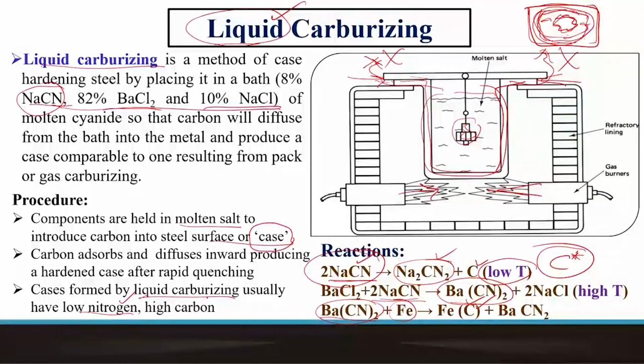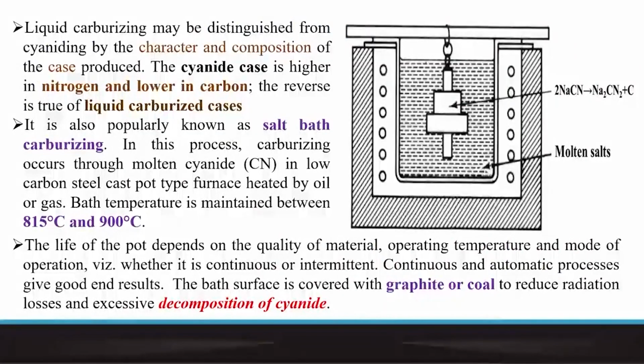So this is to be distinguished from the other carburizing processes in terms of the character and composition of the case that we produce. The cyanide case is higher in nitrogen and lower in carbon, and the reverse is true when we are doing with the liquid bath process. Okay, so it's essentially a salt bath, and the temperature that we are talking about is slightly lower than the pack carburizing treatment, typically about 800 to 900 degrees centigrade.